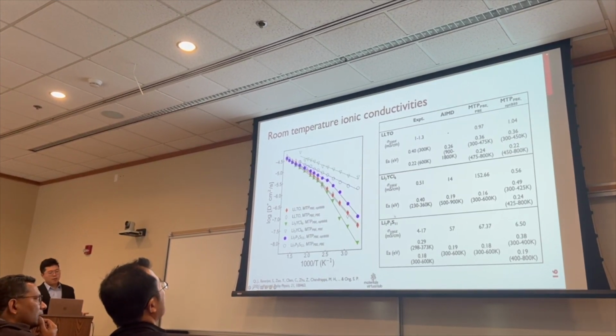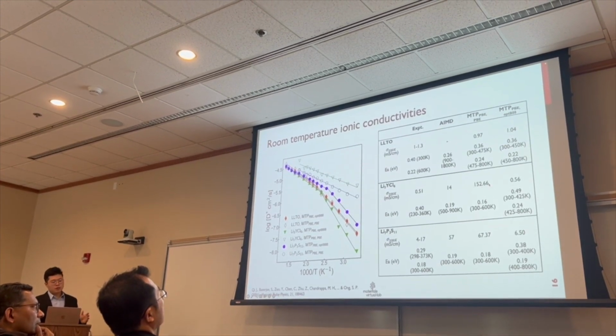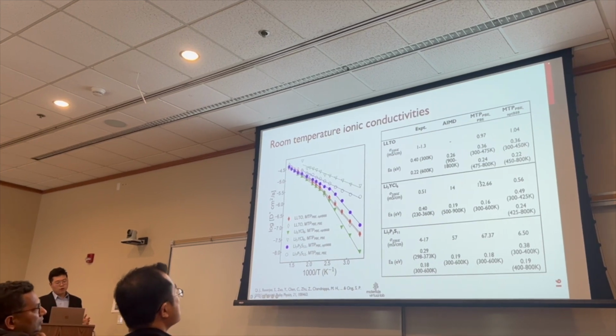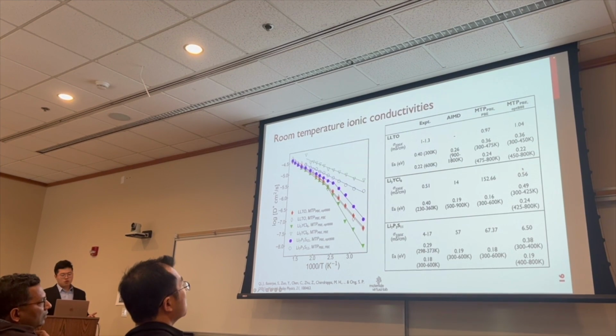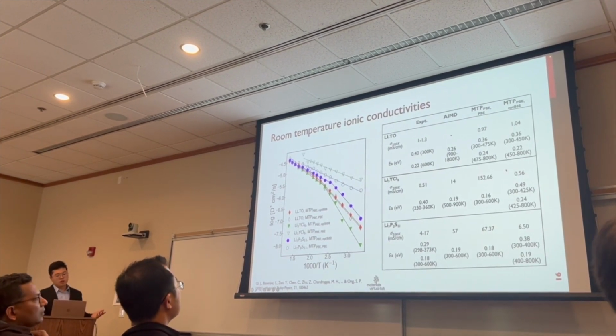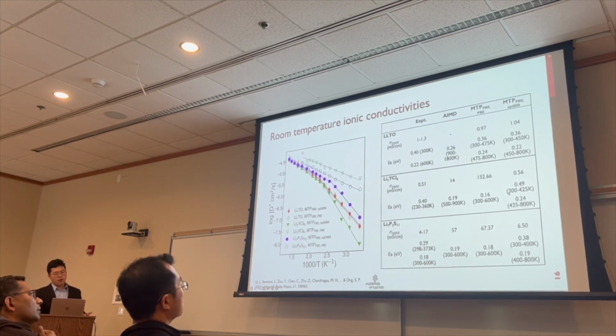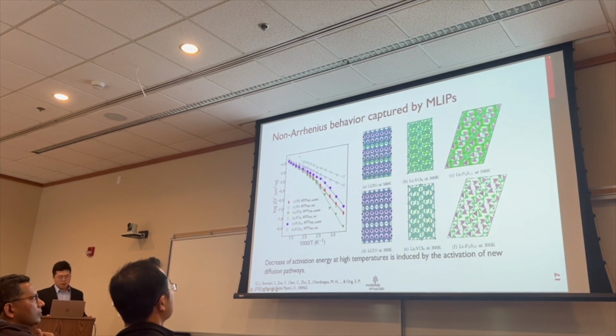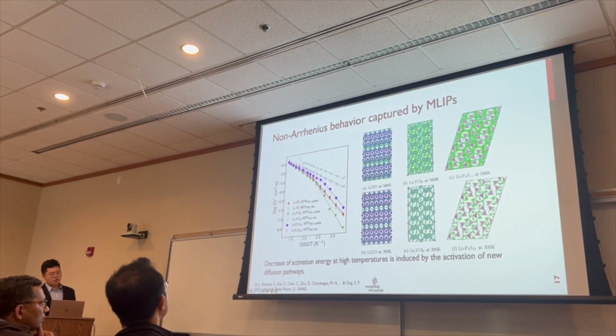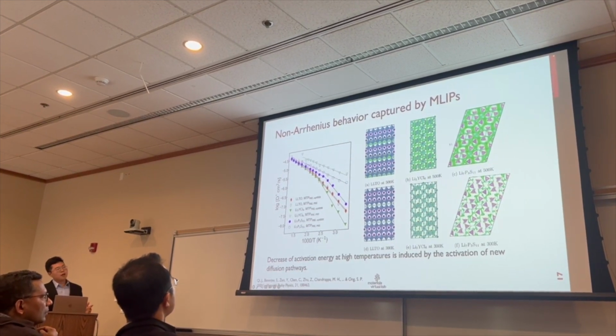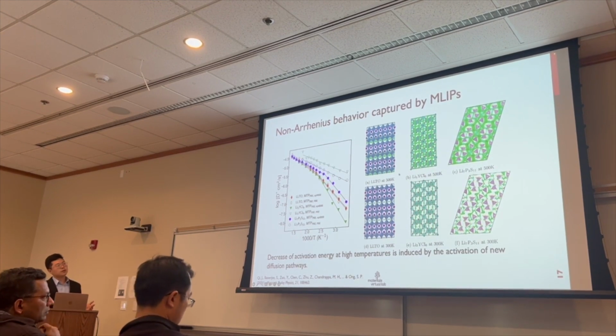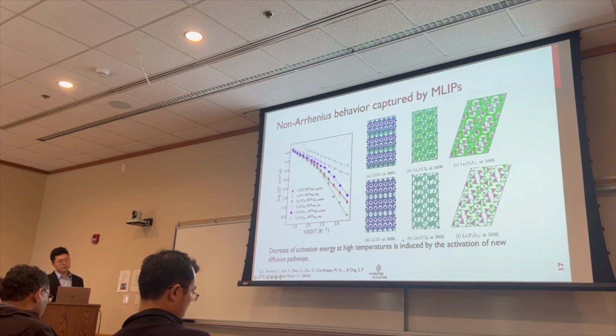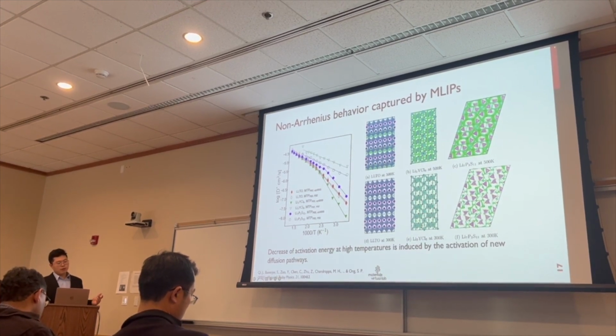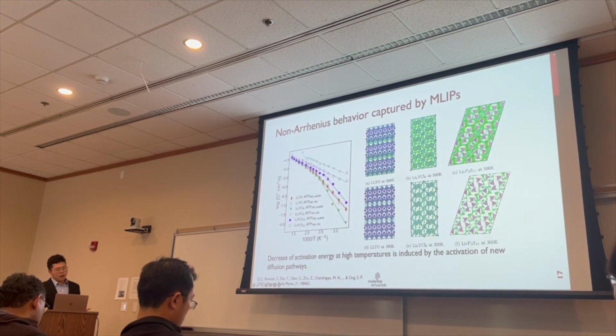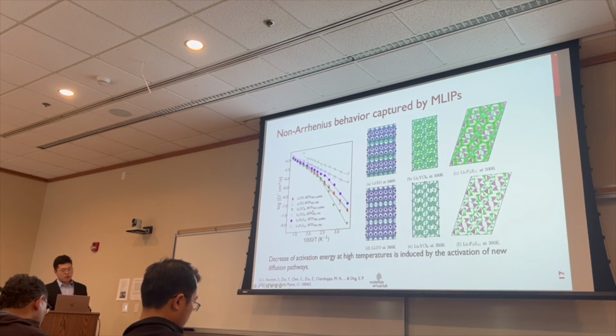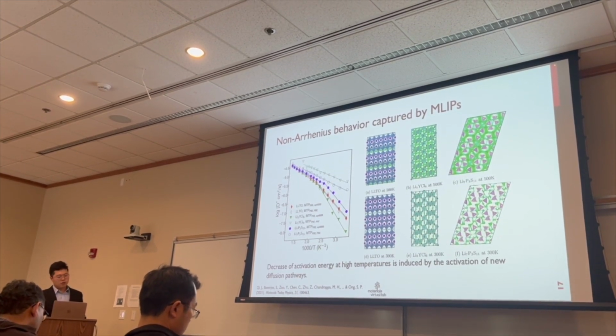For the LYC and LPS systems, we can see that the MTP trained with the PBE functional actually severely overestimates room temperature ionic conductivity, while the MTP trained with the OPTB88 functional gives reasonable matching with the experimental result, and they also capture the non-Arrhenius behavior. We further studied the system by analyzing the diffusion trajectory. In this plot, I give you the diffusion trajectory at two different temperatures, 500 Kelvin and 300 Kelvin, for all those three systems. This is above and below the transition we observe in the Arrhenius plot. And we can see a clear trend: the decrease of the activation energy at high temperature is coupled with the activation of new diffusion pathways.